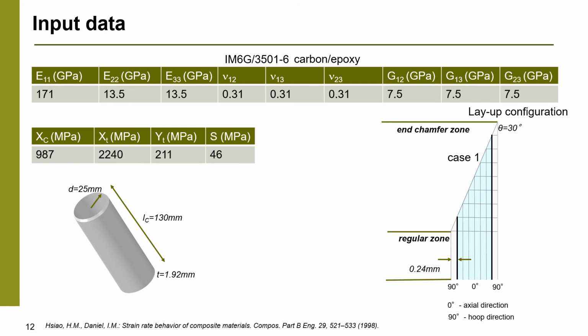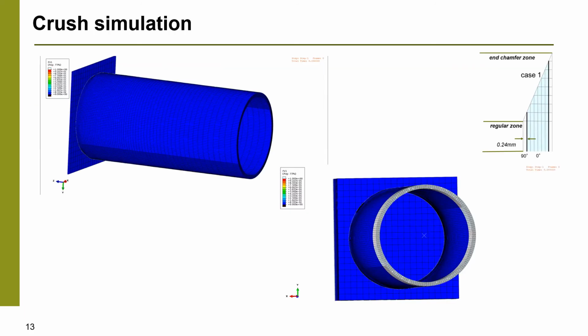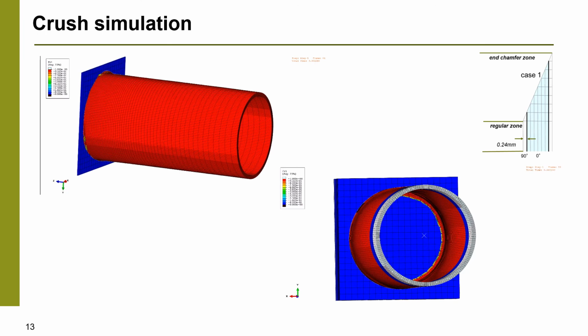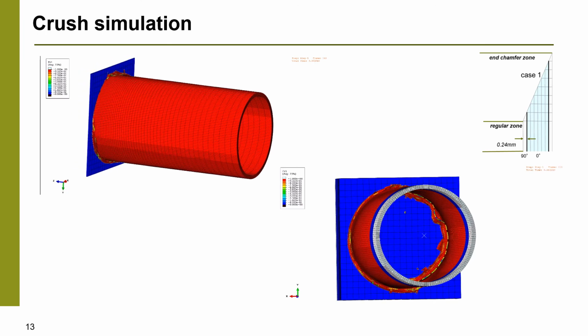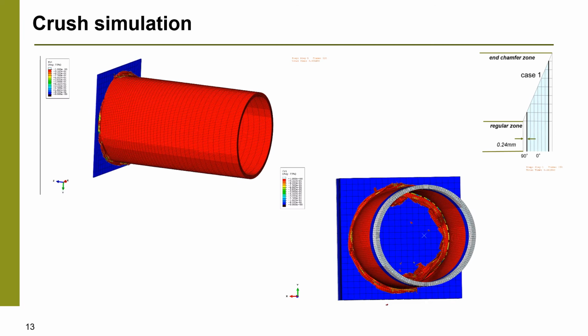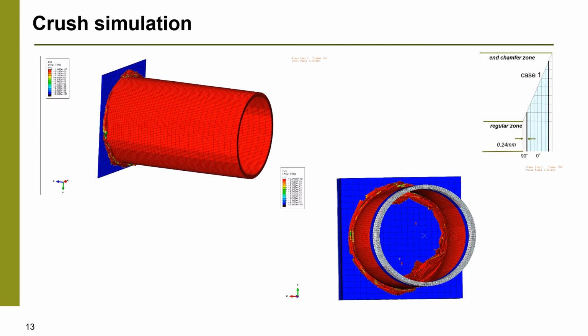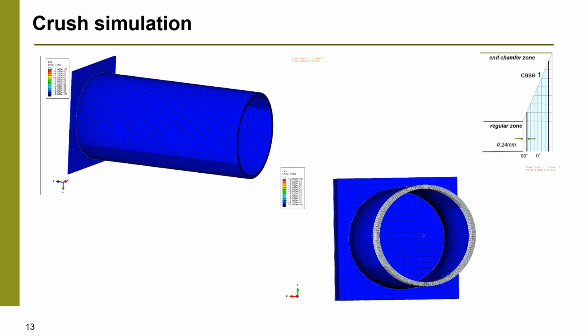So the ratio between axial and hoop fibers is 1:3. This is a simulation of the crash process. Fiber failure is chosen as the element deletion flag. So elements damaged in other modes stay on the picture, and you can observe accumulation of material debris.